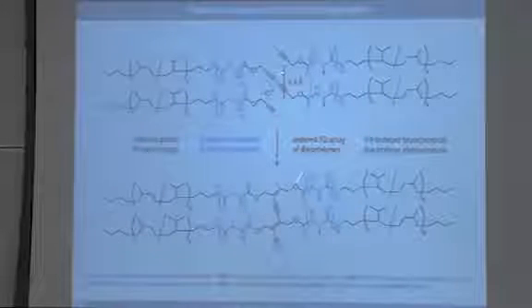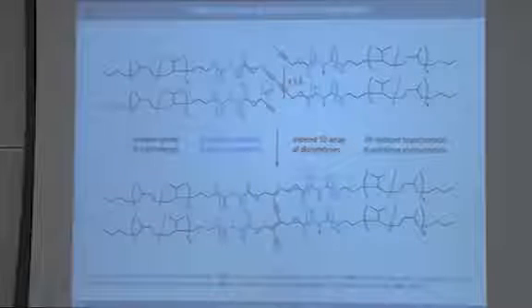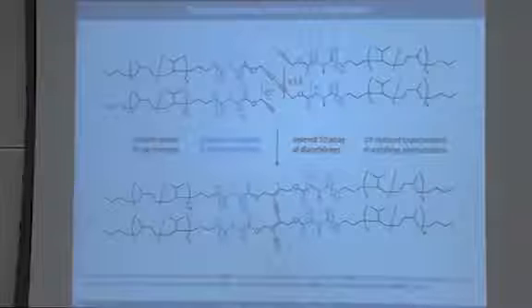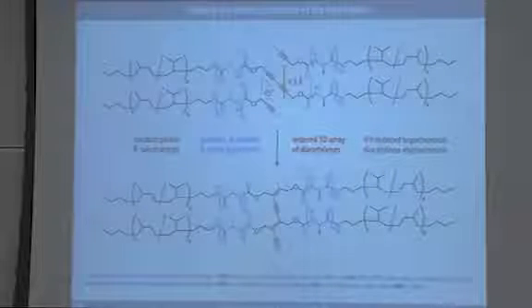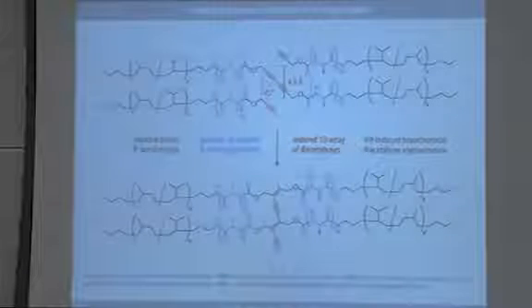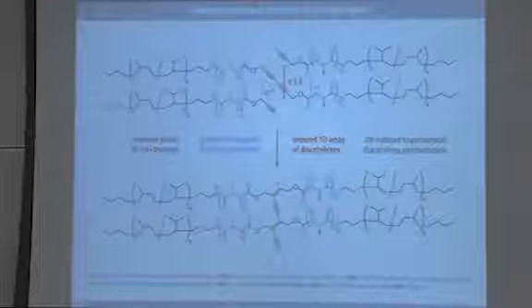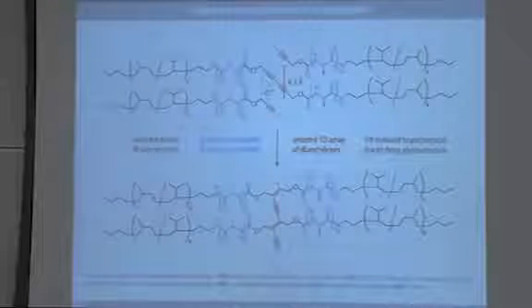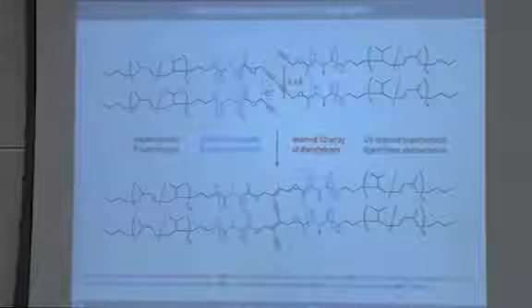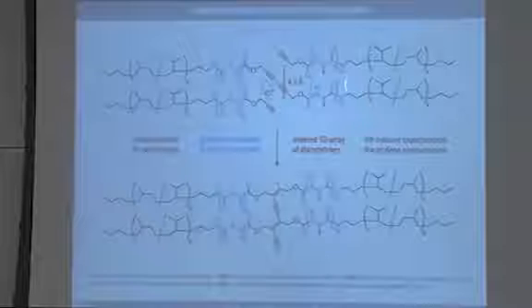We could in addition also use the topochemical diacetylene polymerization shown here as an additional tool to get an idea about the internal structure and the degree of order inside, because this UV-induced polymerization only works if the diacetylenes are present in a highly ordered and pseudo-crystalline, at least one-dimensional crystalline array. Otherwise the polymerization fails. And so if the polymerization works, then this tells you that the internal structure is the same as schematically shown here.